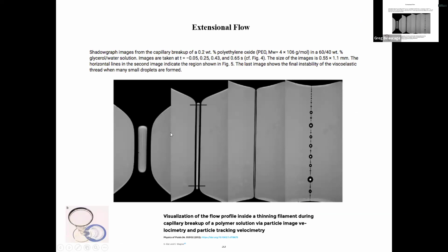when you start orienting the chain. The static measurement is with no flow, but if you start doing things like shadowgraphy, depending on how you pronounce it, which is basically taking a glass cup, shining a light through it, and taking a picture of the shadow of it. To look at flow, it's kind of useful, especially if you use cross polars. You see the oriented chains light up, and everything else is black. Black means there's fluid there, but it's not oriented, and the stuff in the middle is oriented. When it gets to be a very fine